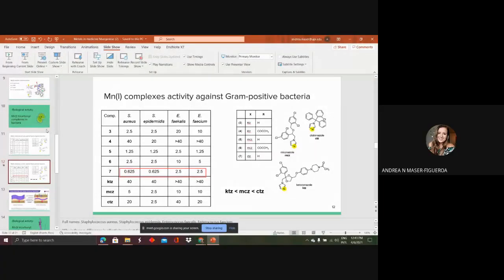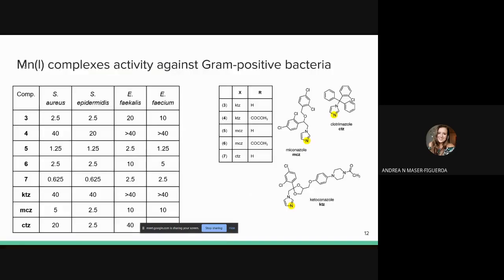All right. Where did I leave off? Yeah, you were at the log... gram-positive, and that there was an improvement over the gram-negative. Okay, thank you. So essentially, they did see a significant difference in the inhibitory concentration for the gram-positive bacteria. As you can see, compound 7, which has CTZ as its ligand, showed 0.625 micromolar as its minimum inhibitory concentration, which is great because it's sub-micromolar. It's very low amounts that inhibited the growth of the bacteria. They also noticed that the metal complexes, generally, save for a few outliers, resulted in more inhibition than just the organic compound alone.